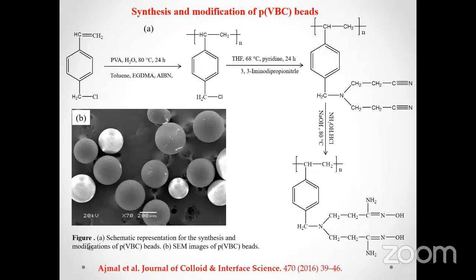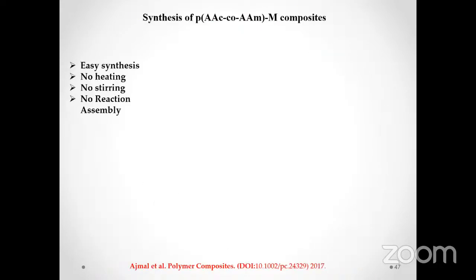I will go through it and move towards the, yes, here is the next improvement. In the previous studies, we have prepared our microgel systems in a temperature controlled assembly where the hydrogels were prepared in the presence of an inert atmosphere using nitrogen or argon. But after going through those steps, we thought, why not develop some alternate methods which can be cost effective, which can be time effective, and which should need low labor. And then we developed another strategy for the synthesis of hydrogel.